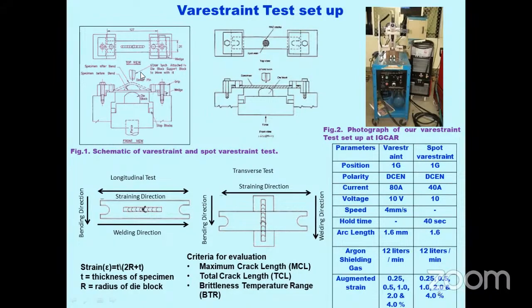So this is the Varestraint test method, that is, the variable restraint test method. We have several variations in this test method. Like the spot Varestraint test method, in which we evaluate the HAZ cracking susceptibility; a weld spot is created and the HAZ formed surrounding the weld is characterized for its susceptibility to cracking. In the longitudinal test, we see the weld metal as well as the HAZ for cracking susceptibility, where the direction of welding and direction of straining are parallel. In the case of the transverse Varestraint test, the direction of welding and the direction of the applied bending strain are perpendicular. In that way, the weld center is targeted and we evaluate the weld metal cracking susceptibility.